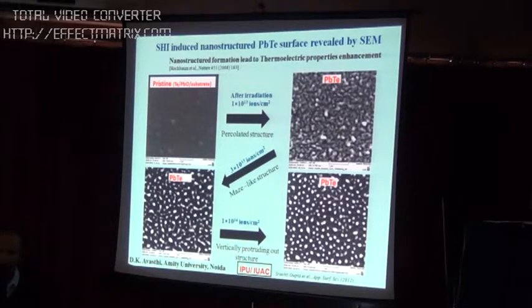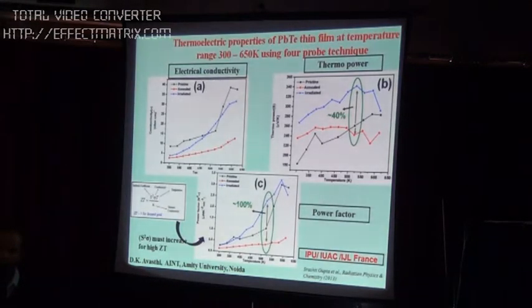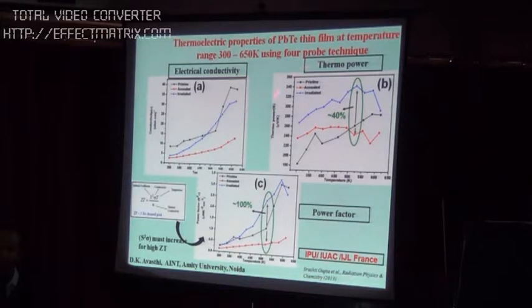Okay, so we did some measurements on this. Let us concentrate on this. Here you see the thermopower at different temperatures. This is for the pristine. If you anneal the same thing, then it is here. But if you do the irradiation, then there is formation of lead telluride. Then you see it has gone up here. So there is a clear-cut gain in the thermopower efficiency.